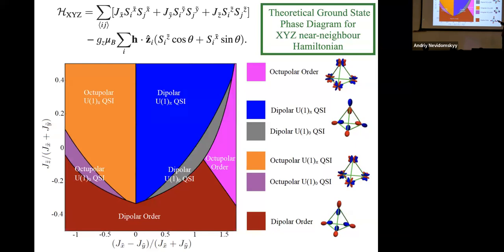But this is the general phase diagram for this system. And actually, it's a very attractive phase diagram from an experimental point of view. And that's because a lot of this phase diagram, actually everything above the line that I'm tracing out here, are quantum disordered ground states, right? So these are all versions of quantum spin ice, but quantum spin ice where either the dipolar degree of freedom or the octopolar degree of freedom dominate. And those basically dominate depending on which of Sx or Sy dominates or is bigger, right? Which of those two terms in the Hamiltonian is bigger.